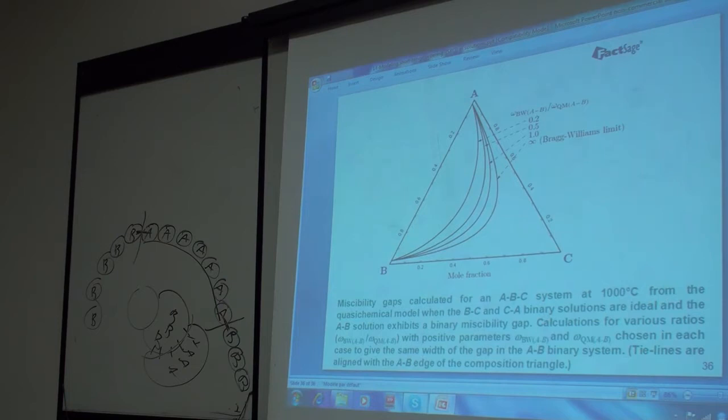So anyway, that is the... It's a shame we can't do the quasi-chemical model with the entropy term correct, because then I think it would work out correctly. But maybe even then it wouldn't, because the quasi-chemical model is not properly taking into account second, third, fourth neighbors. It's only about nearest neighbors. So you might still have to put in the Bragg-Williams term for the higher order terms.